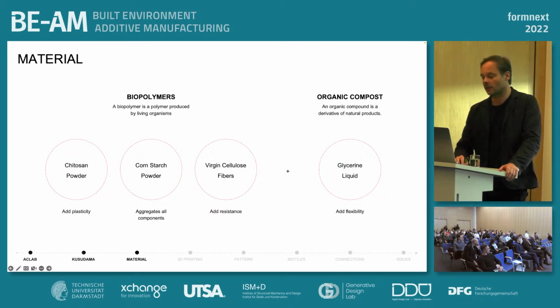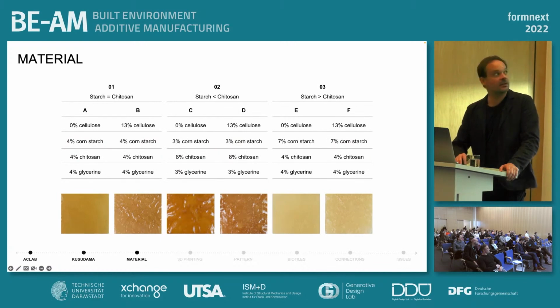Considering this, our aim on this specific research was to start testing materials based on biopolymers such as chitosan, starch, and mixing with cellulose fibers. We know that chitosan would introduce some plasticity, the starch would help with the aggregation of the mixtures, and cellulose fibers introduce some resistance. Finally, we are using liquid glycerin to give some flexibility to the composites. Here, just a set of material samples made and tested with different percentages of raw material.